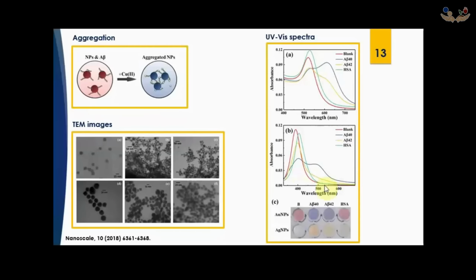Therefore, we have two patterns, one of them from gold nanoparticles and another from silver nanoparticles. Here you see the color of our probe. We have two responses for each analyte. Blank is red, and this color for gold nanoparticles and silver nanoparticles. The pattern for amyloid beta 40 is completely different from human serum albumin or amyloid beta 42.